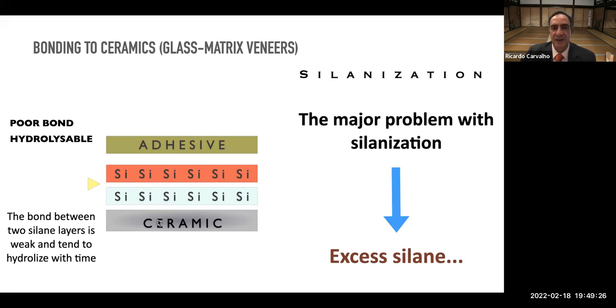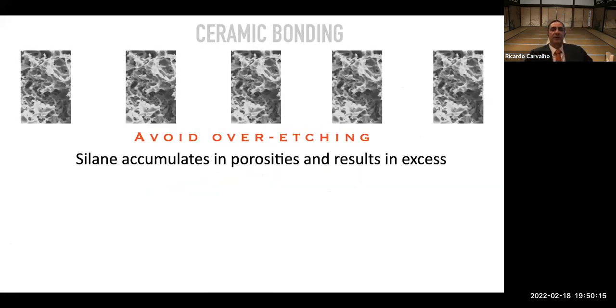The bond between the first layer and the ceramic is very stable and tends to last forever if there is no physical removal. But if you apply excess silane, layer after layer of silane on top of each other may eventually hydrolyze and degrade over time. So this might be a clinical failure down the road when your veneer simply debonds or detaches from the surface. And then when you look at your veneer, you'll see that most, if not all, of the resin cement remained attached to the tooth surface, and the veneer just pulls out clean. That is exactly a silanization problem that you might have overcome.